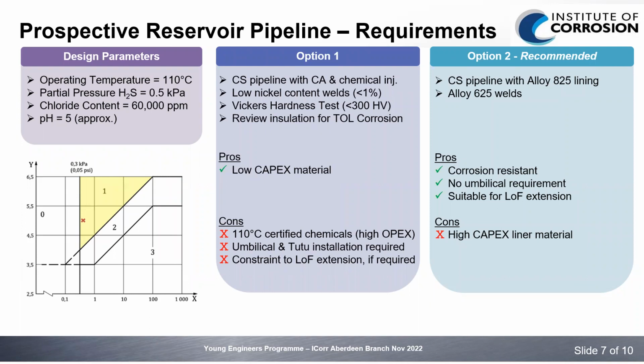The pro for this option is it's low capex, it's carbon steel. However, the cons are that because of the higher temperature, we may need certified chemicals, especially for this service and injection, and that could lead to high OPEX cost. In addition, we would need to install an umbilical in the tie-in as well to facilitate chemical injection, which may offset the lower capex of the material. Also, because the carbon steel is part sacrificial, there is a constraint to life of field extension should that be an option further down the line, or any future tiebacks.